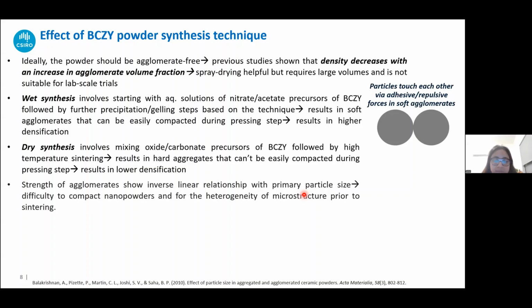However, in the dry synthesis process, the agglomerates that are formed are basically hard aggregates. They have a bridge in between them, like you can see in this figure, and the individual particles are clubbed into each other. So they can't be broken down easily, and that basically leads to lower densification upon sintering. Now, some recent studies have also shown that the strength of the agglomerates follows an inverse relationship with the primary particle size. So this makes it difficult to compact nanopowders and leads to heterogeneity of microstructure prior to sintering.